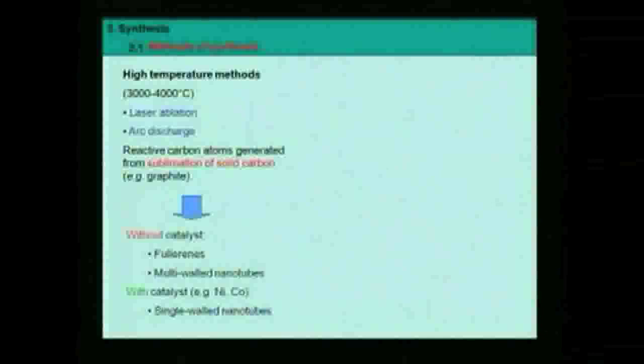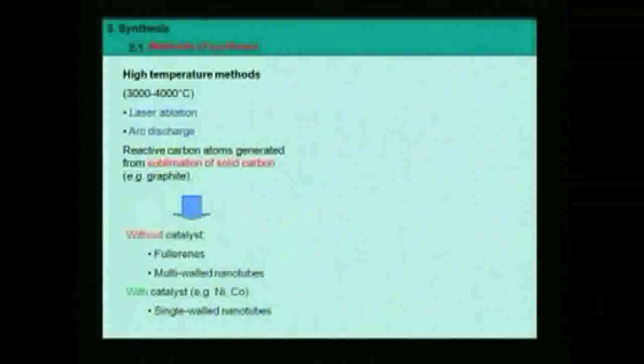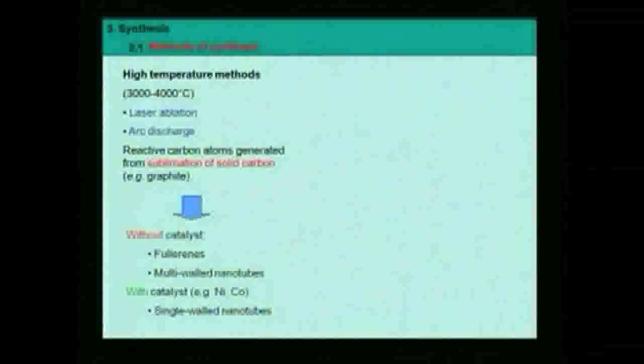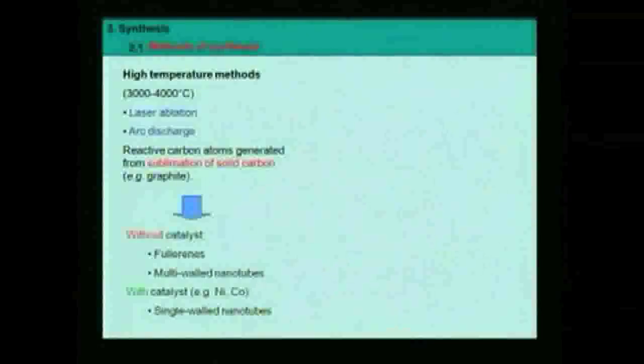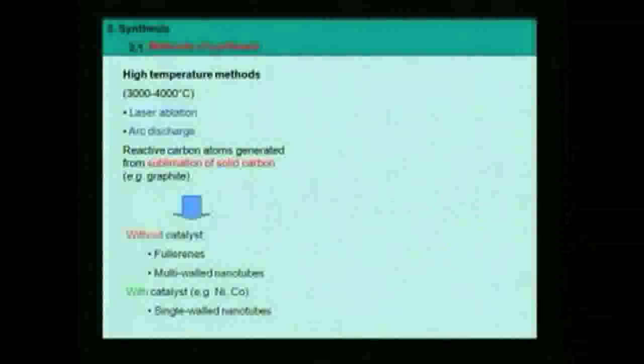There are 2 different ways to do that. You can mix catalyst together with graphite, and this catalyst will be sublimated together, and during the cooling you will form also small metal catalyst particles, and thanks to this you will form a special type of objects, which are the single wall nanotubes that we have already discussed yesterday. Without catalyst, this is the original method, what you will obtain is either fullerenes in some conditions or multi-walled nanotubes in other conditions. But you will never obtain single-wall nanotubes if you do not mix a catalyst together with the carbon source, graphite.